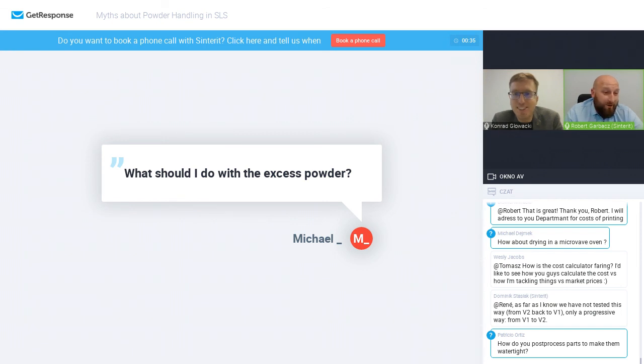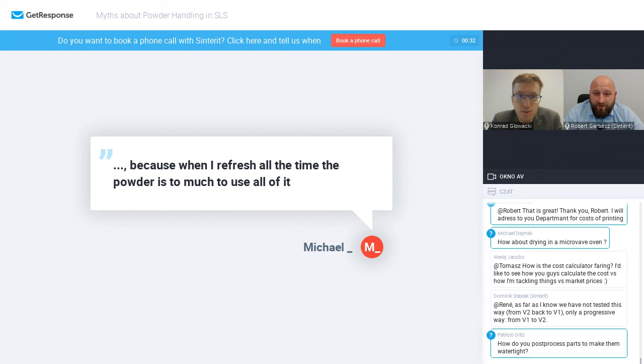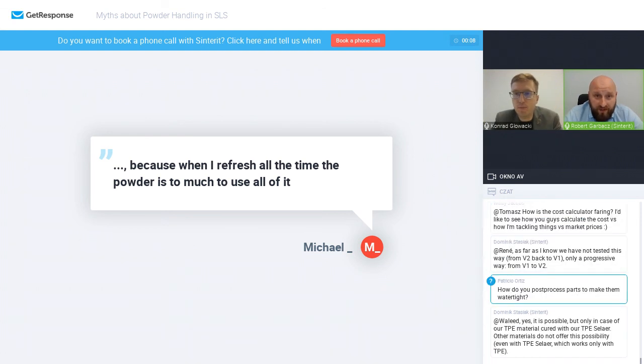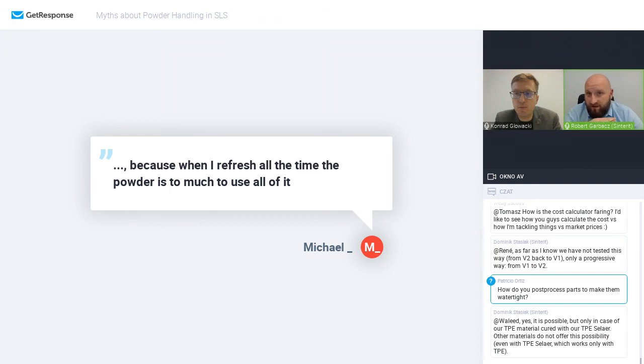So you will also have the same surface at your place. What should I do with excess powder? Because when I refresh all the time, there is so much powder to use. Yes, it's a common SLS thing that you are generating more and more powder. The simple solution is, if you have like 10 liters of excess powder, so you have 20 liters of powder, print with this powder 3 times without refreshing, so it will definitely offset the cost of this powder, because when you are not refreshing it, you will be at zero total, and then throw the powder out. You can print with our powders 3 times, even more, without refreshing it.